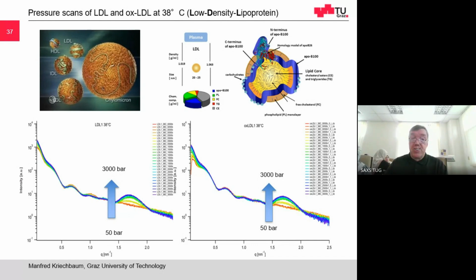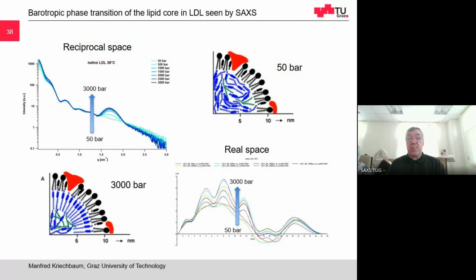So in the nanostructure space, what does it mean? We have here 50 bar, and at 3000 bar, you see an ordering of the inner core. So the core gets structured, and the more structured it gets, the more pronounced the peaks get. On the other hand, the same happens with the enveloping protein. This gets denatured. But the main effect here is the ordering of the inner lipid core.